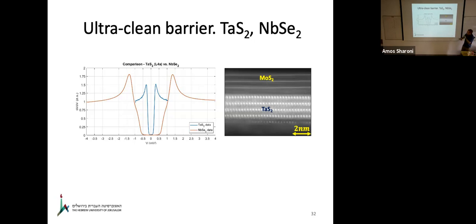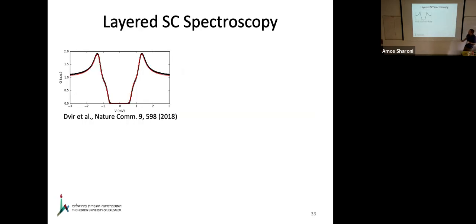other. And this is an example of measurements we've done on niobium diselenide and tantalum sulfide. These are tunneling measurements. That's most of what my group does, this kind of tunneling spectroscopy. And generally what you see is the superconducting gap. It's well behaved, it's called a hard gap property. That means that you only have tunneling. You don't have any other processes.